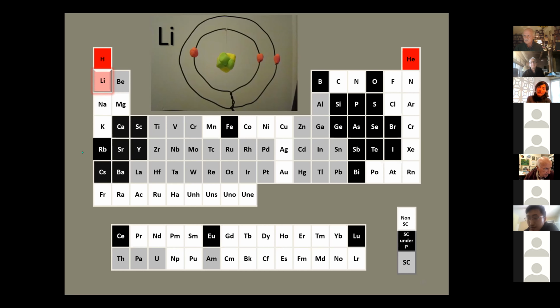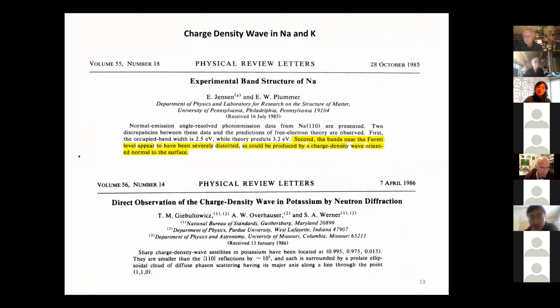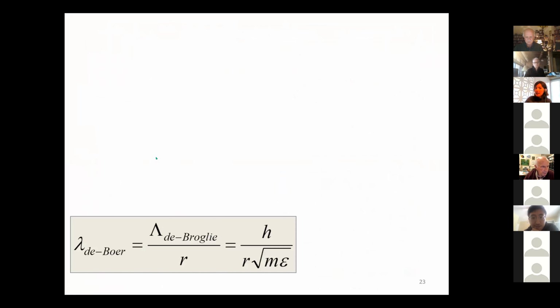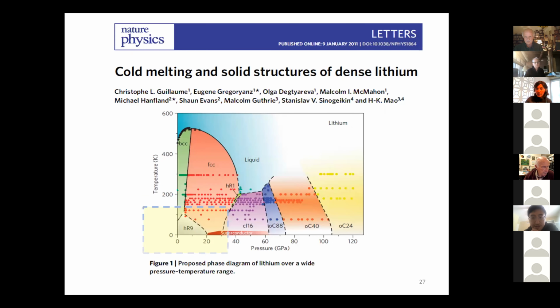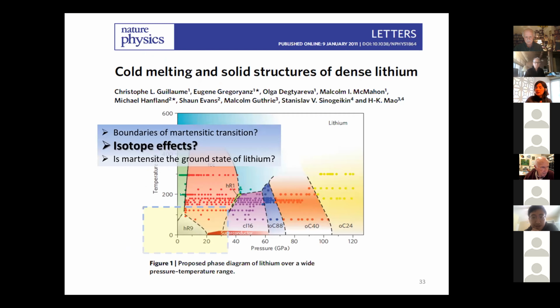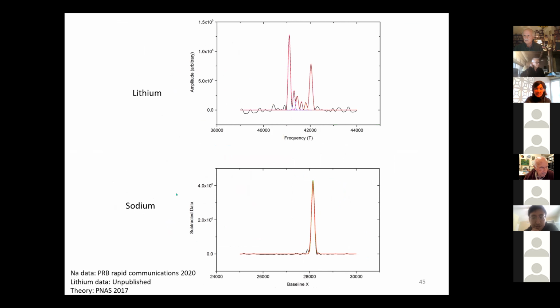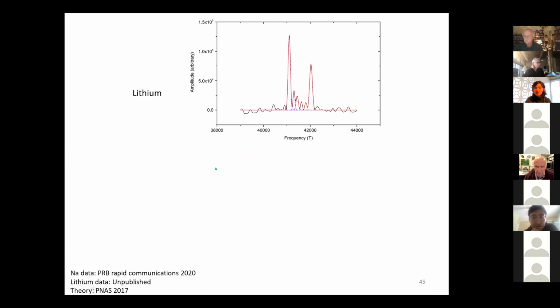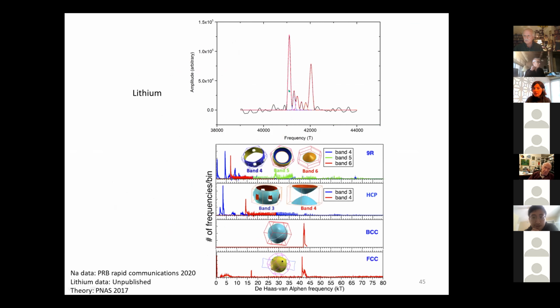What we can say is how the Fermi surface looks like. And we are working closely with theoretical groups that, for different structures, calculate the Fermi surface. And we compare with our quantum oscillation measurements. So for example, this is an example. This is the spherical part of the Fermi surface of lithium, with quantum oscillations, and these are different structures, how they should look. Right. And by comparing these with these models, we can get an idea if the structures that we think are in place for some of these elements or materials are consistent or not.